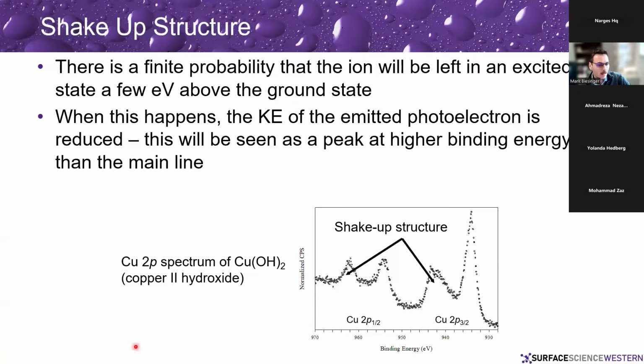And so if we look at the copper 2p spectrum of copper hydroxide, this is the classic shake-up structure we see for copper 2 species. And we see that this structure above the peak here is what we're having.